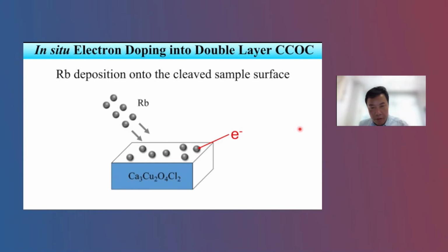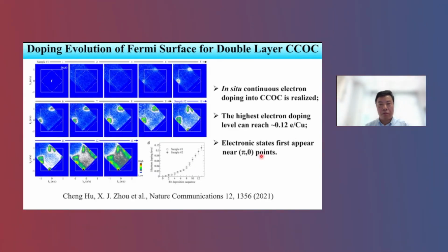Then usually, how do we dope the parent compound? In our ARPES system, we dope the system by depositing some rubidium on top of the surface. And in this case, it can dope electrons into the CCOC system. So by gradually increasing the deposition, we can increase doping. So then this is the measurement of the Fermi surface. Without doping, there's no spectral weight at the Fermi level. When you increase the doping, you start to see something near the (pi, 0) points. This spectral weight just increases with increased doping. So eventually you can form some Fermi surface near the (pi, 0) points. And later on, you can form some states along the nodal direction, eventually forming the large Fermi surface.